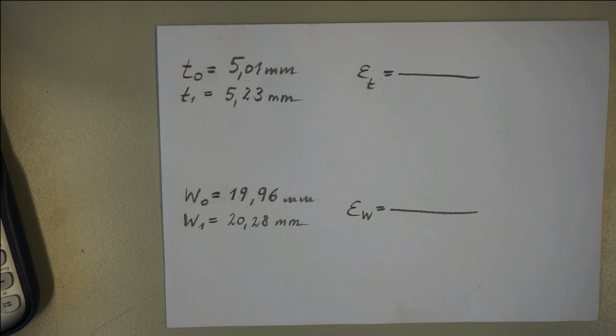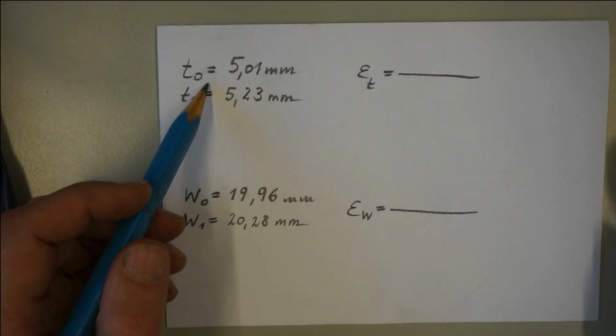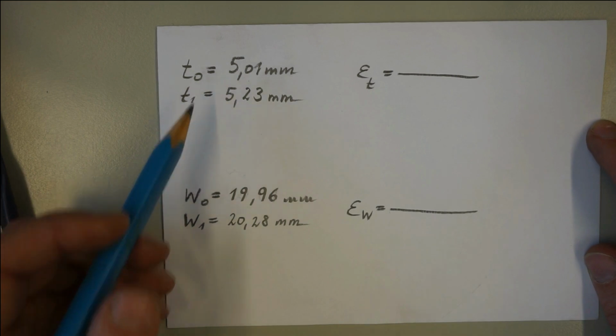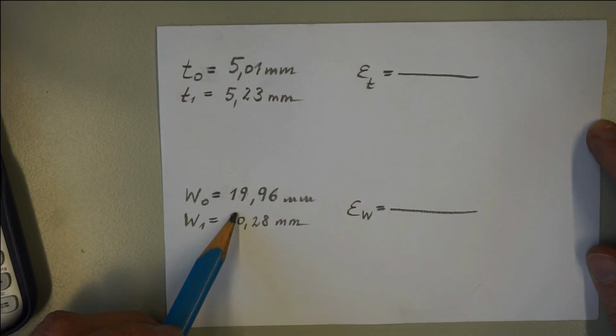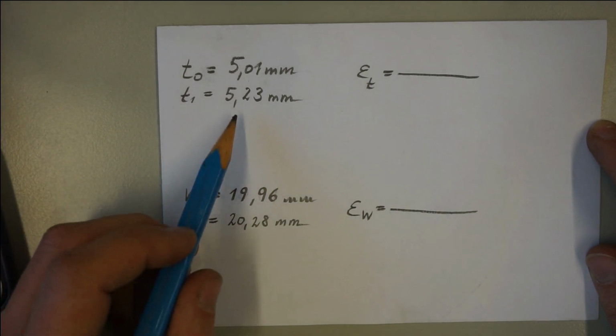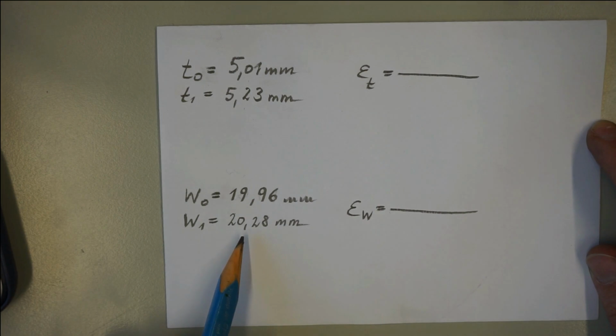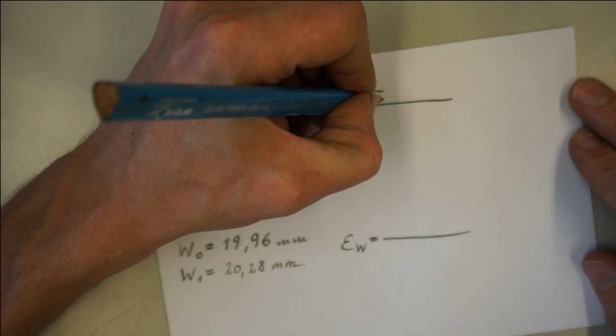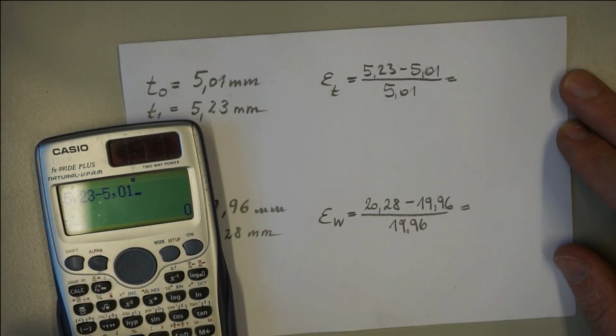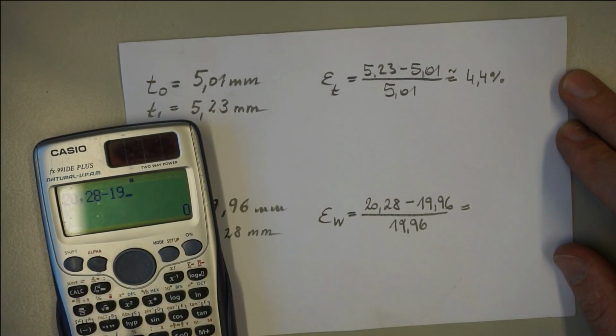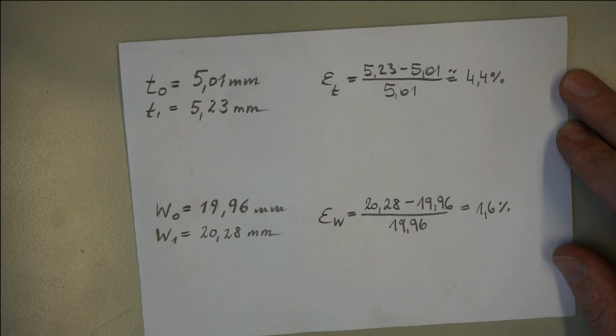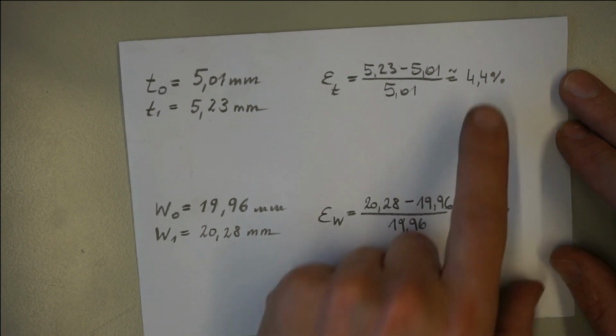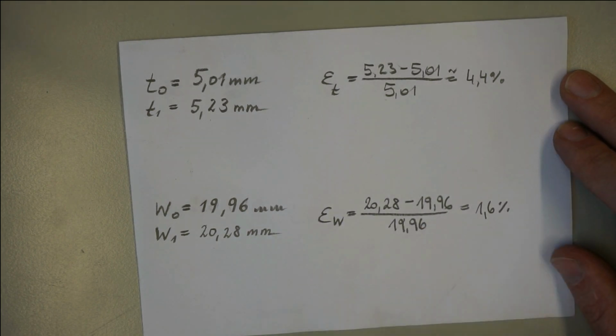Off camera I noted the initial cross-section dimensions of the central bar. They were 5.01 millimeters in thickness and 19.96 millimeters in width. After the experiment we found a thickness of 5.23 millimeters and a width of 20.28 millimeters. This equals a thickening of 4.4% and a widening of 1.6%.